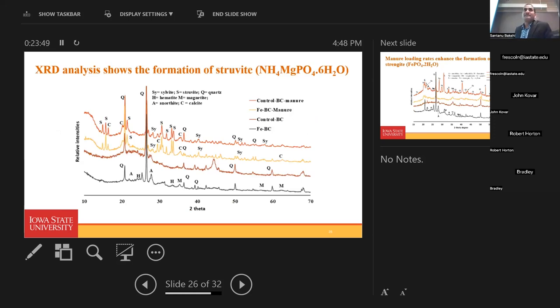Next is the X-ray diffraction analysis. We did iron biochar, control biochar, iron biochar with manure, and control biochar with manure. We found several minerals. Quartz, hematite, anorthite, and one more, these minerals we found in the biochar. When we treated with the manure, we found a new mineral called struvite. We also found sylvite, and we also found calcite. Struvite is ammonium magnesium phosphate, so phosphate is preferentially absorbed onto the magnesium phase rather than the iron phase.